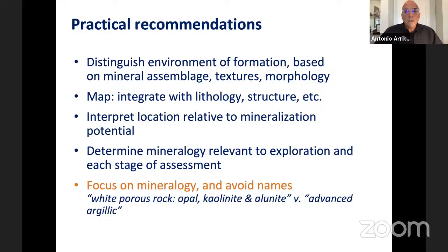Spectral tools are phenomenal. They are a phenomenal complement. They can help you distinguish minerals that are very hard or otherwise impossible to distinguish except with XRD, pyrophyllite from kaolinite, possibly from alunite even. So they are a fantastic complement to the previous.